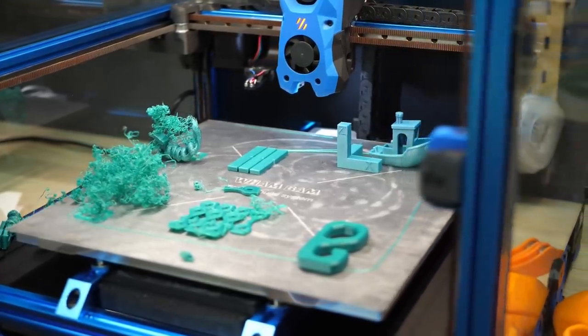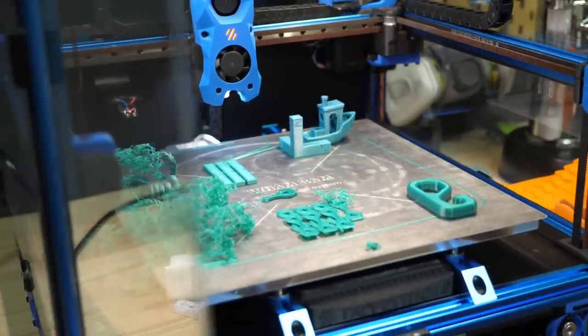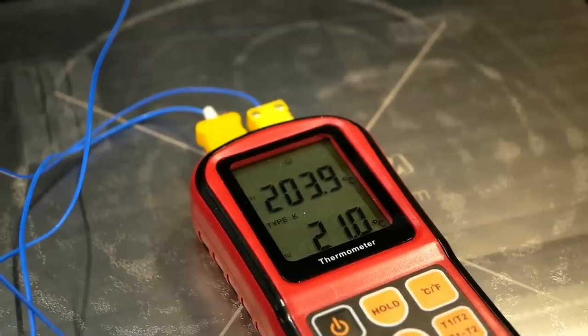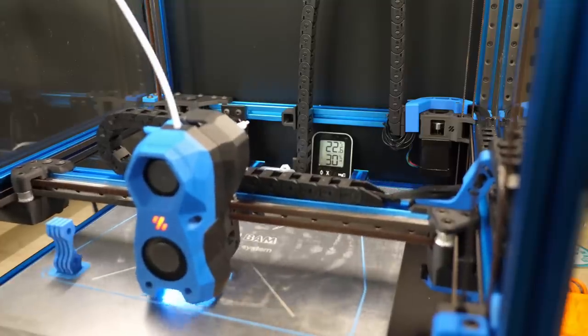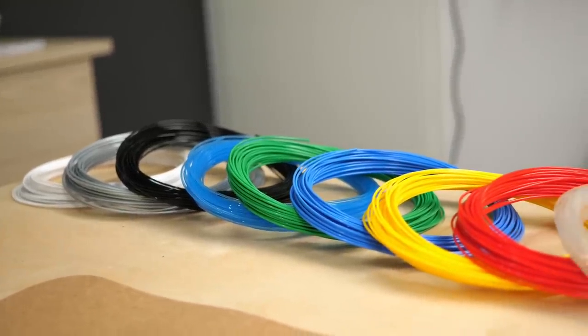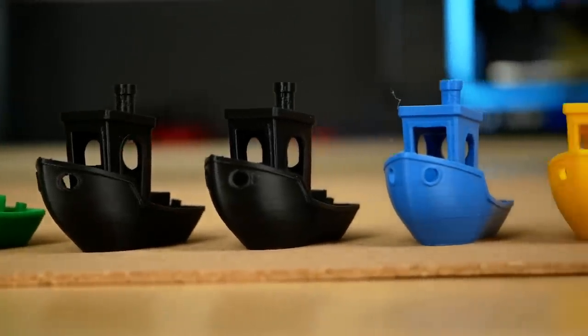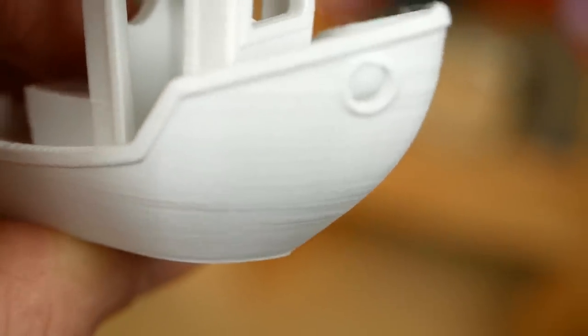Until I had everything set up, I noticed that the print head of my Voron 2.4 was bigger than I expected, knocking parts off and resulting in layer shifts and failures in my first prints. Since I usually treat filament colors from the same supplier as interchangeable, I used exactly the same G-code for all 10 prints. I printed the PLA at around 204°C nozzle temperature, 60% cooling and 60°C bed temperature with open doors, so at around room temperature on my Voron 2.4. Some will argue that they tune every color of their filament, but in my opinion that would defeat the purpose of this investigation. The general quality of the parts was very nice as you would expect with PLA. The only notable thing was that the white filament hugely amplified inconsistencies in the print, which is also the reason why I rarely print in white.